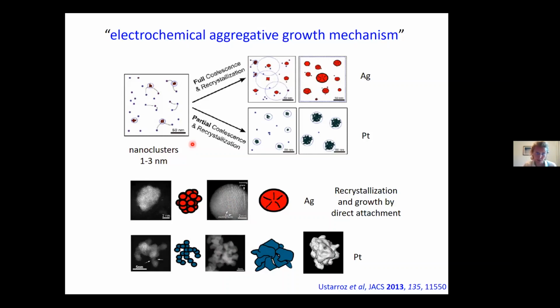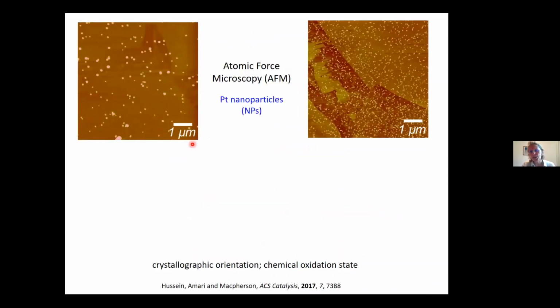And this was really interesting to us, this short-term nucleation and also John's use of TEM in this way. We'd ourselves looked at atomic force microscopy images of metal nanoparticles, and this is a study we did on platinum, and we were looking at electro-oxidation of an alcohol. It's work by Hussein, and the AFM shows smaller particles here, larger particles here. These smaller particles were more active, catalytically active to the oxidation process. And you could argue, well, it's because they're smaller.